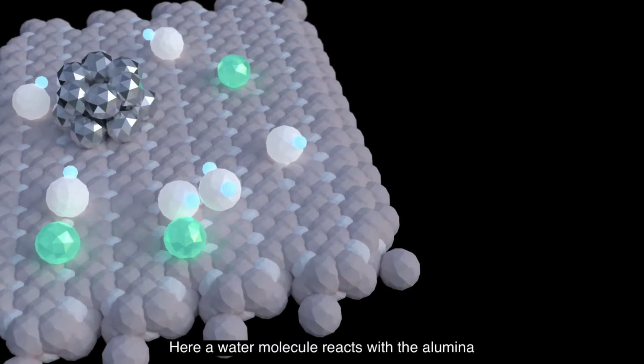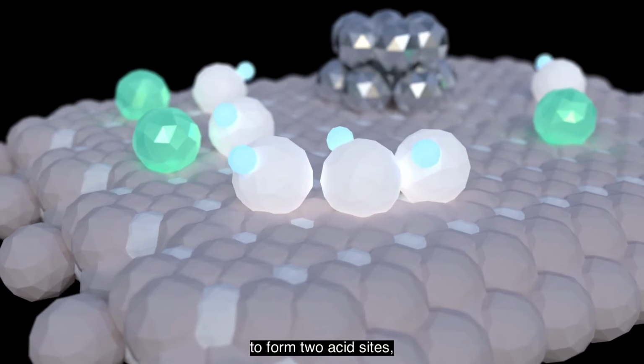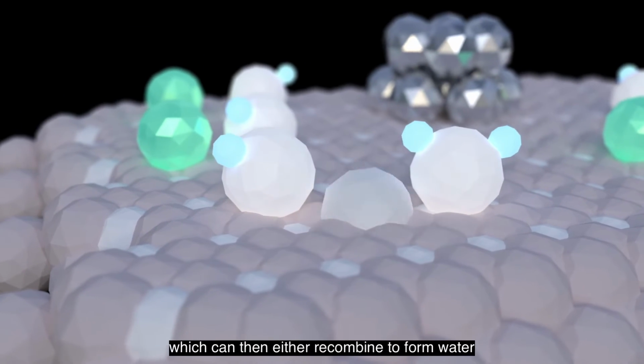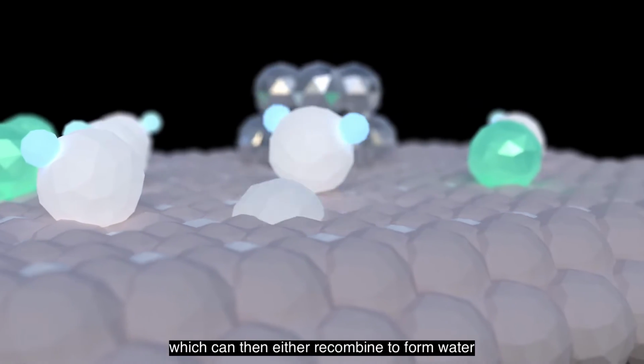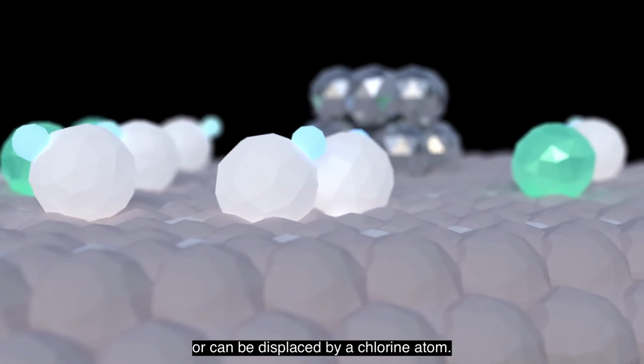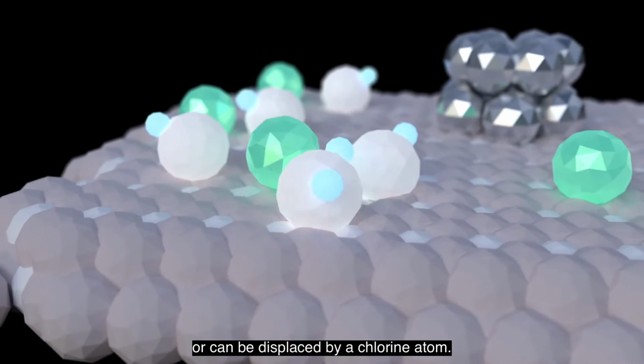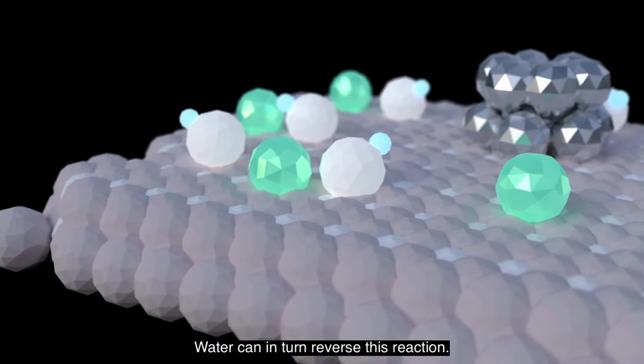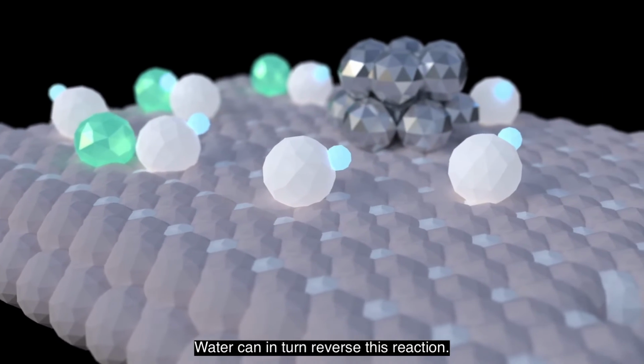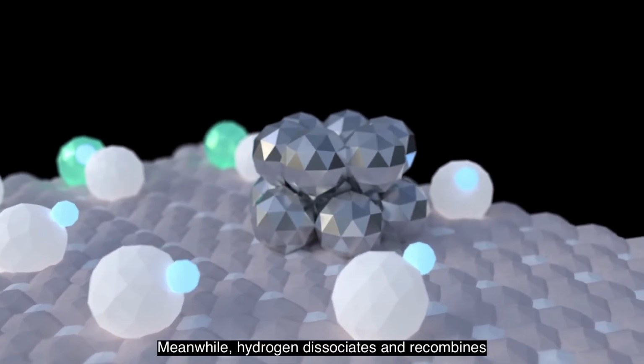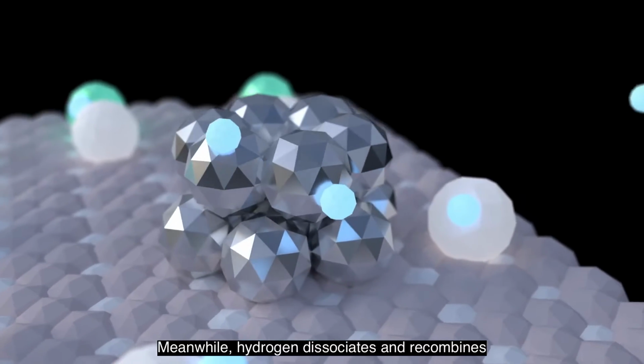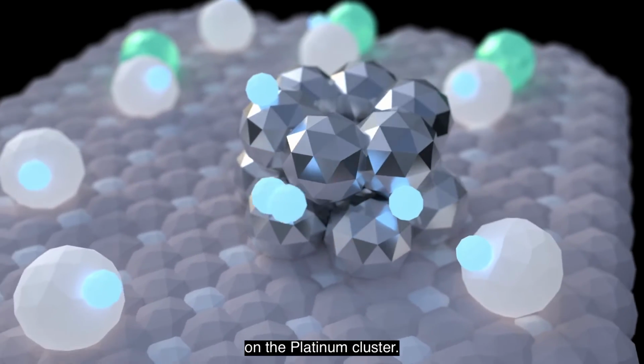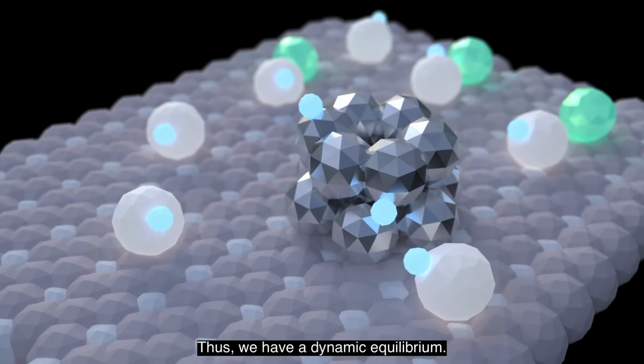Here, a water molecule reacts with the alumina to form two acid sites, which can then either recombine to form water or can be displaced by a chlorine atom. Water can, in turn, reverse this reaction. Meanwhile, hydrogen dissociates and recombines on the platinum cluster. Thus, we have a dynamic equilibrium.